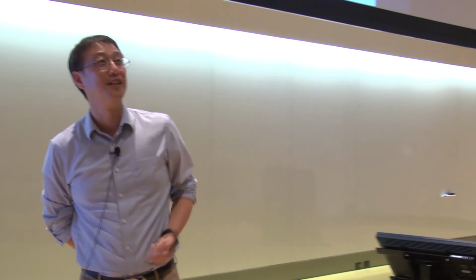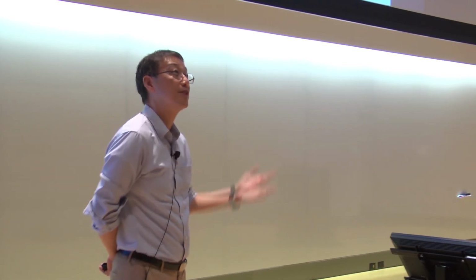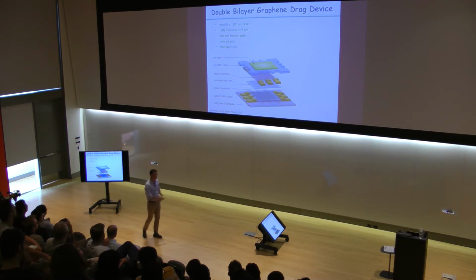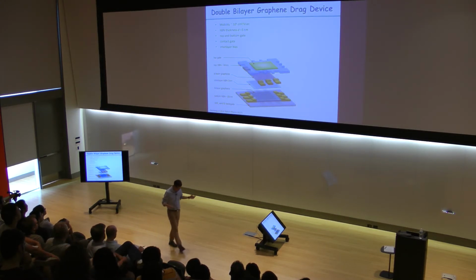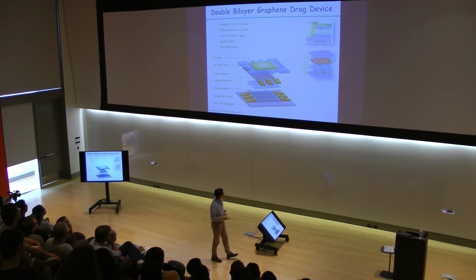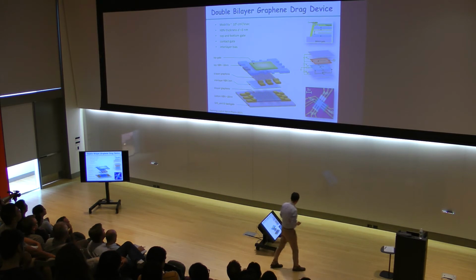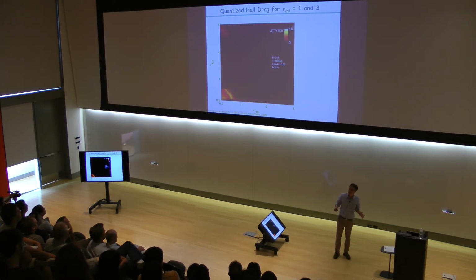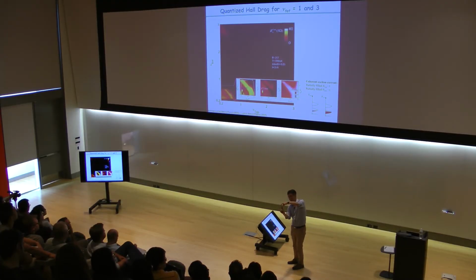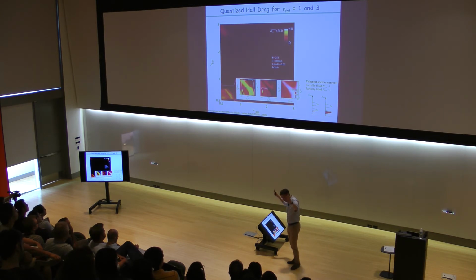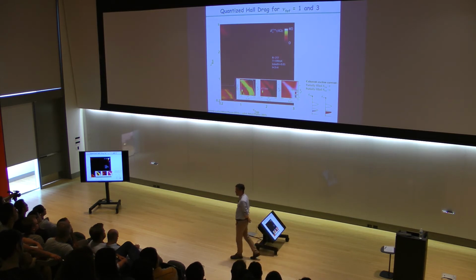Now, of course, in two-dimensional electron systems such as graphene and boron nitride, as long as your layer is clean, you can repeat this in graphene, right? Well, here is the device. We have two graphene layers separated by boron nitride with top and bottom gates, and each of the layers has contact. As I mentioned, this can be done. And this is the real device image. When you apply the magnetic field and measure the drag resistance, indeed, like in gallium arsenide, we do see that the drag resistance is quantized, right? So the quantum Hall effect in one layer is connected to the other layer, although electrically they are separated, right?